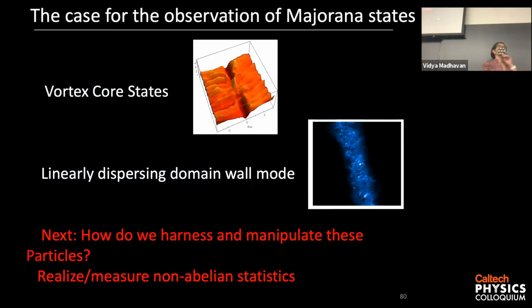And so in this material, I hope I've been able to show you that we see two kinds of features. One is these vortex core states, for which there's mounting evidence that they behave like Majorana fermions. And the other is that if you have the right kind of domain wall, like a stacking fault of the right kind, then at the domain wall, we see evidence for these propagating states.